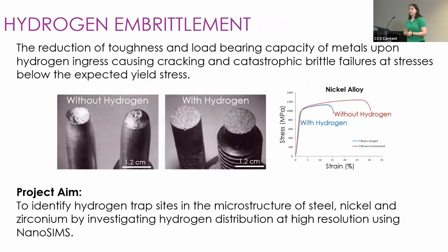What I want to focus on today is how we've been using the NanoSIMS to look at hydrogen embrittlement. I'm hoping that most of you will be familiar with this, but just as a quick summary, when you have hydrogen inside your metals, for example, you often get a reduction in toughness and load-bearing capacity of those metals. And what you can get is cracking and catastrophic failure of that material at a much lower yield stress than expected. We can see that in this graph here: without hydrogen, this nickel alloy would fail at this point. But as soon as you have hydrogen in that material, it fails much earlier than expected. And you can see the difference here in the fracture surface as well, brittle versus ductile failure.